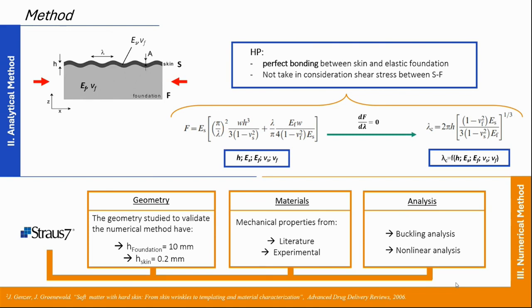Numerical simulation is the second method. We use this tool to validate the analytical approach. We use Straus7 to recreate the soft membrane that has a 0.2 mm skin thickness to reduce the influence of the infinite foundation. A skin-to-foundation thickness ratio of 1 to 50 is set in the numerical model.